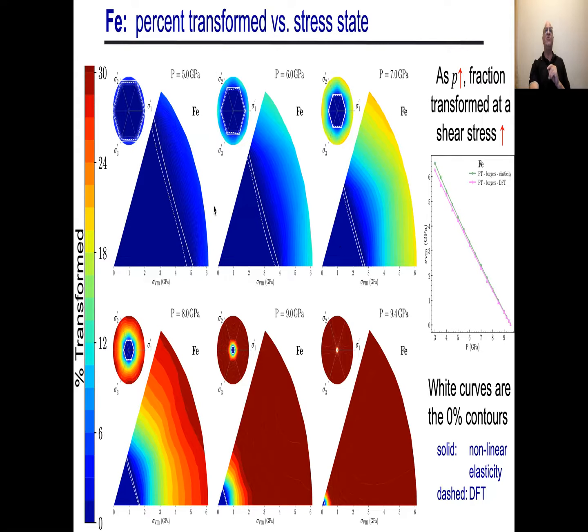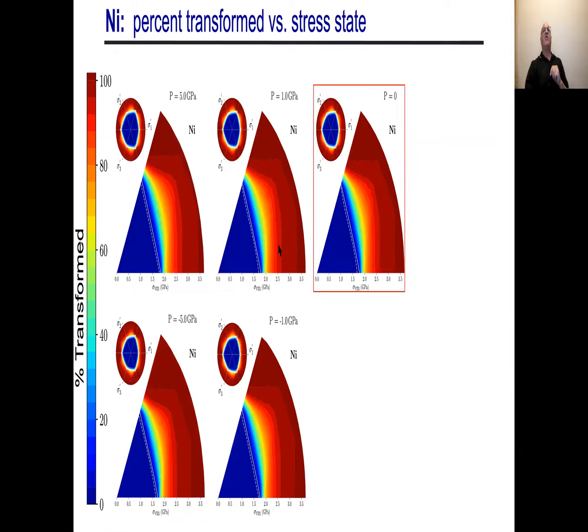The other conclusion is if I compare the elasticity result with DFT-informed elasticity with a full DFT calculation along the entire surface, what you see is that it's not too bad. So third order elasticity seems to work okay. Now, let's shift to nickel.